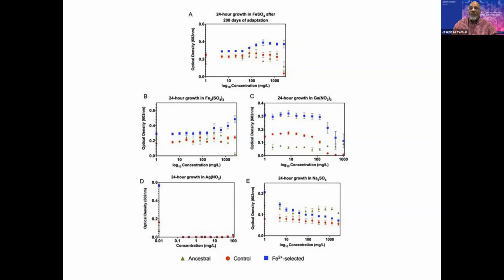Now, when we compare them in gallium 3, now gallium is an iron analog. It has almost the same ionic radius as iron does. And so gallium has been proposed as an antimicrobial with the idea that you could quench iron siderophores because they won't be able to tell the difference between gallium and iron. Now, we've done experiments demonstrating that bacteria can evolve resistance to gallium as well, but again, I'm not talking about those results here. But what we see interestingly in this experiment is that iron 2 resistance also powerfully provides gallium resistance relative to the controls and the ancestor.